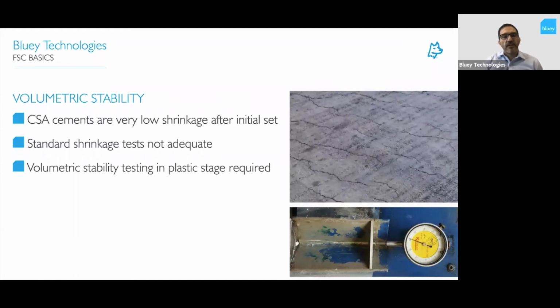CSA cements are very, very low shrinkage after initial set. We're talking shrinkages of around 200 to 300 microstrain, much, much lower than what you see out of concrete. But the standard shrinkage test in that regard isn't fully adequate. It gives you an idea of the shrinkage that happens from 7 to 28 days. And yes, CSA is a very low shrinkage in that zone.